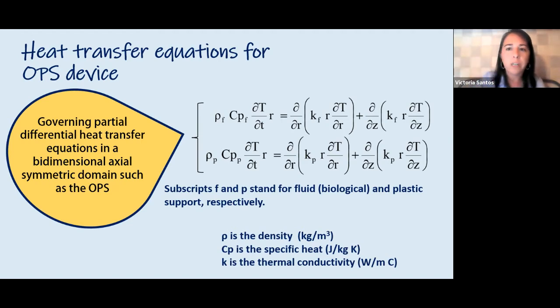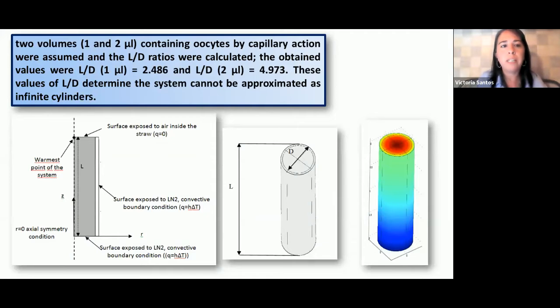If we solve all these equations that are second-order derivatives and in transient state, we can find the temperature as a function of radial and axial coordinates and time at each point inside the device. So the OPS system, we have 2 volumes, 1 microliter and 2 microliters, and we calculated the length over the diameter, and it was 2.4 for 1 microliter and 4.9 for 2 microliters. So this cannot be approximated as an infinite cylinder. We had to use a model where it was a finite cylinder.